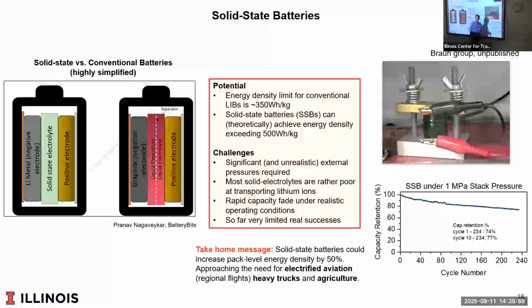By the way, one of the most popular ones is sulfur-based, and so it doesn't exactly burn, but it gives off large amounts of hydrogen sulfide gas when it's heated. That may not be better than burning. H2S, forget the smelling part of H2S. At high levels, it's extraordinarily toxic. So there's work to be done.